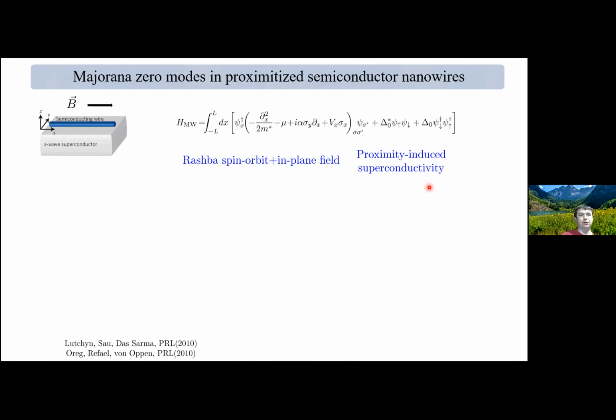So the essence of this approach is that we take a quasi one-dimensional wire, contact it with an S-wave superconductor, and in a simple realization, one can just apply a magnetic field along the direction of the wire. In this wire, there are semiconductors where a large spin orbit coupling appears due to the inversion symmetry breaking at the interface. And this inversion symmetry breaking couples spin and orbital motion. That's one of the key ingredients, because we want to remove one of the spin degrees of freedom in order to make a spinless superconductor, right?